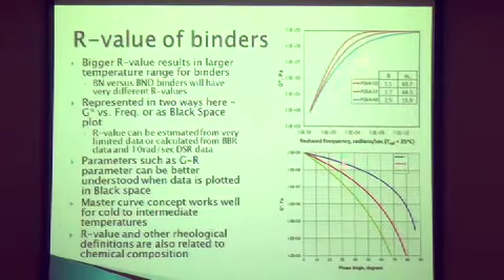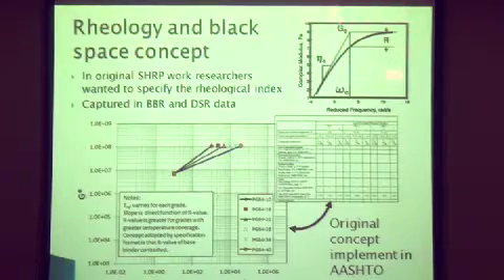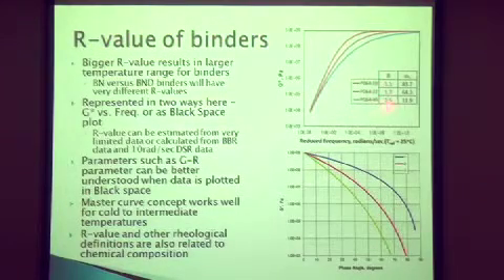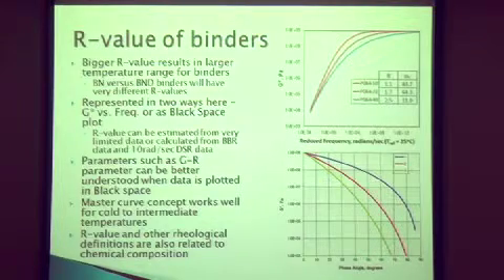This shows binders. It's really the same plot as this, but I've got here three different values of rheological index. I've got frequency, I've got modulus. The rheological index of 1.1, 1.7, 2.5. 1.1 is a PG 64-10. And you can see how the shapes change. And this data, plotting G star versus phase angle. Same data.